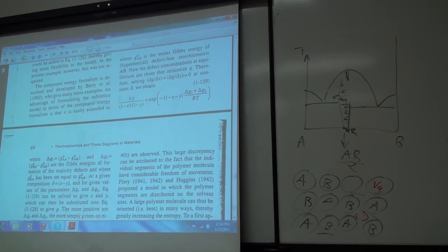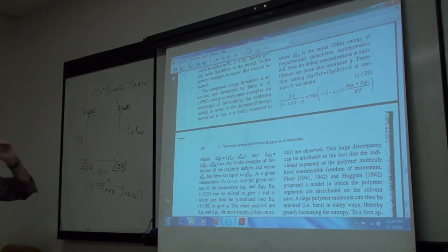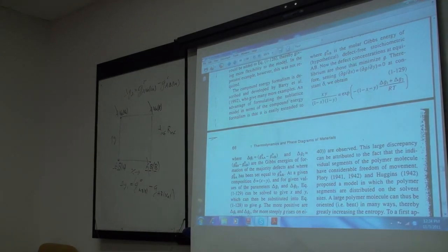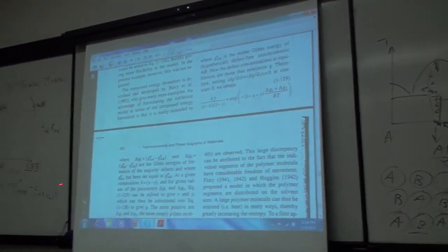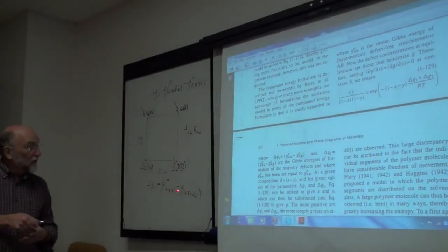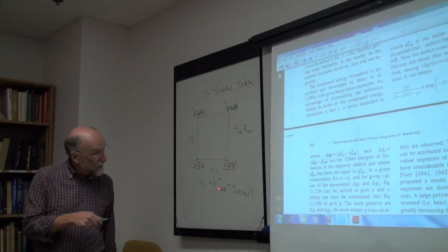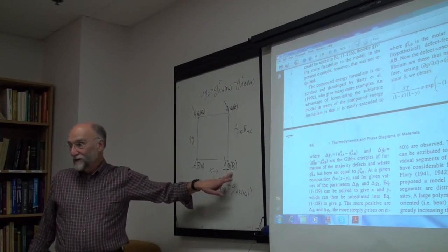But once again, we have a different model, vacancies and interstitials. It very easily fits into the compound energy formalism without having to come up with a different model every time. But again, the important thing is to separate your model parameters, which have physical meaning, from your formalism parameters, which have no physical meaning. If you had no data on the system but wanted to make some sort of estimate, this is what you should be estimating: the energy of forming a vacancy, not the Gibbs energy of this thing, which is a hypothetical affair. You should be estimating the Gibbs energy of that. That's your model parameter. This is not a model parameter, it's a formalism parameter.